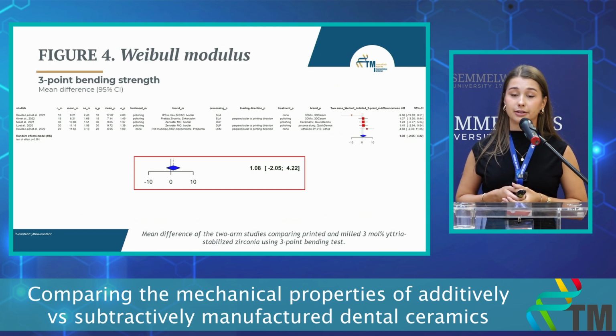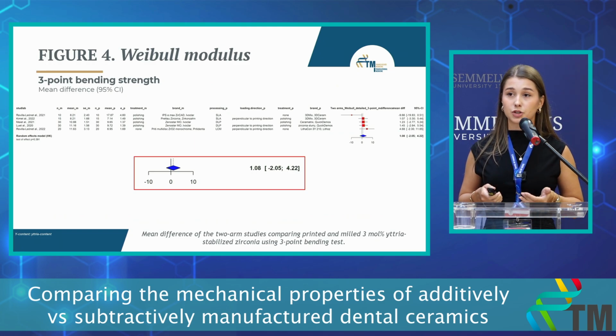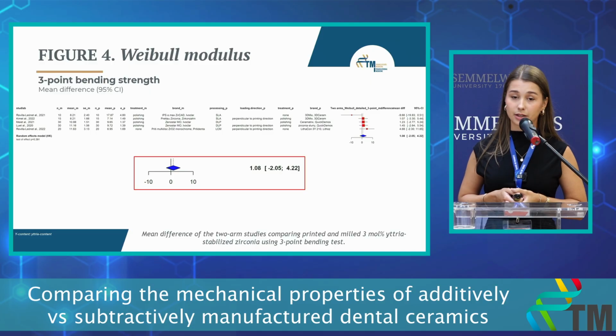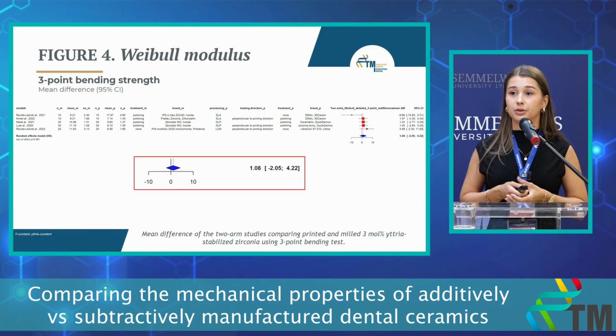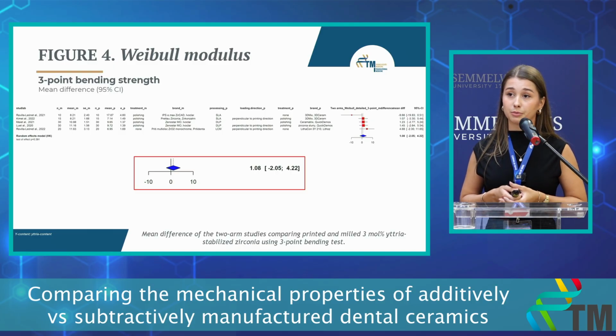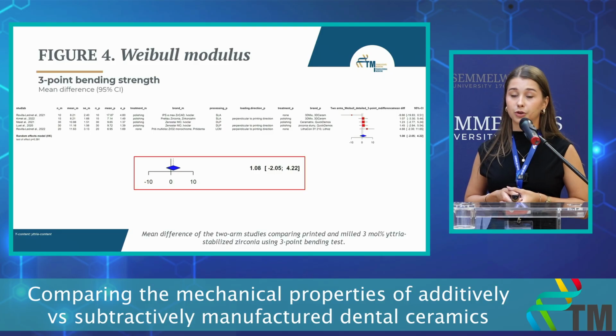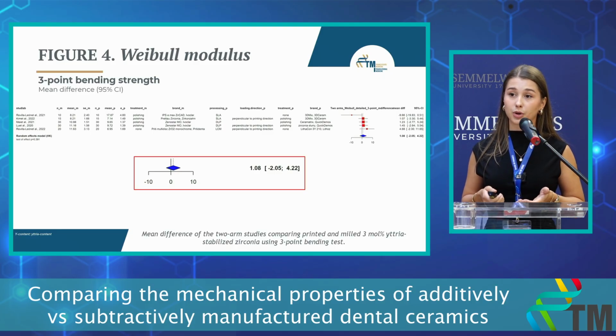We investigated Weibull modulus as well, so this shows us the reliability of the strength data. Here we can see the results for the 2 arm studies, which shows us the difference between the Weibull modulus of printed and milled zirconia, measuring the 3-point bending strength of the material. We have an overall mean difference of a little bit more than 1.